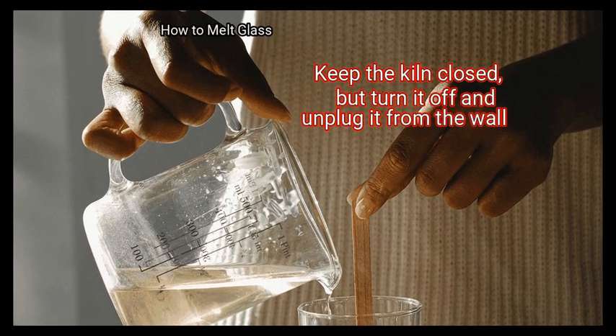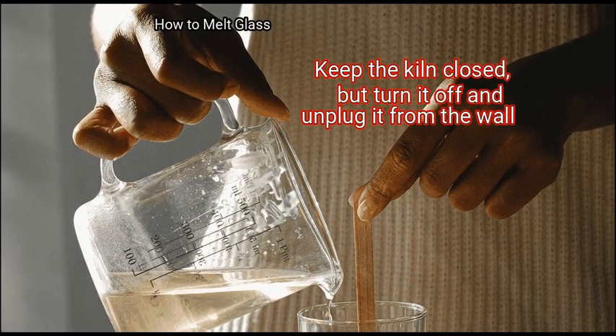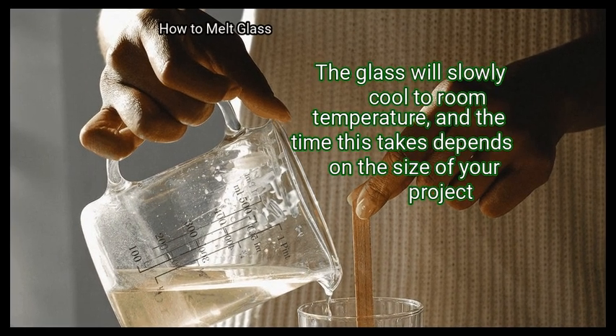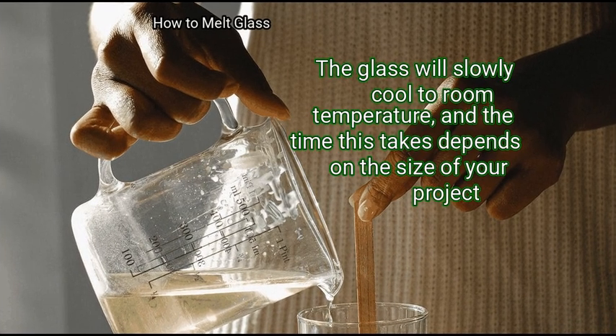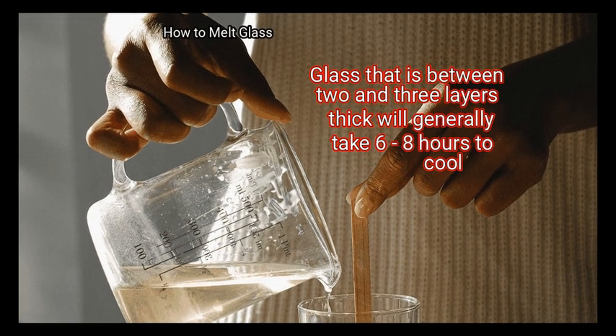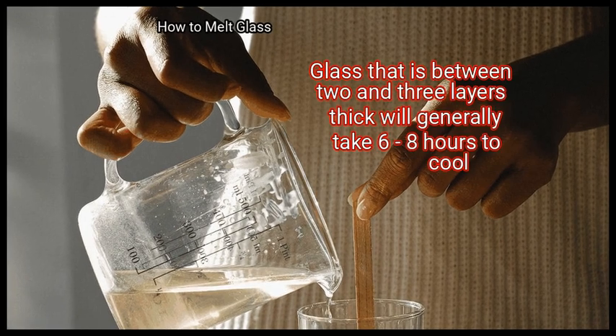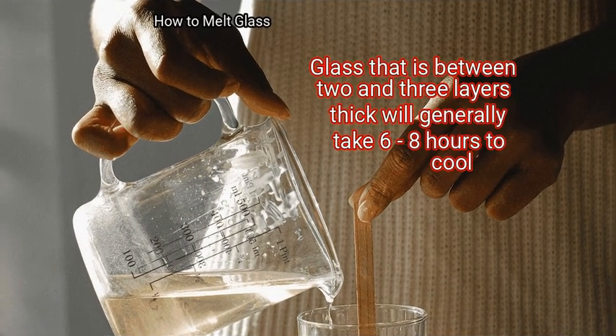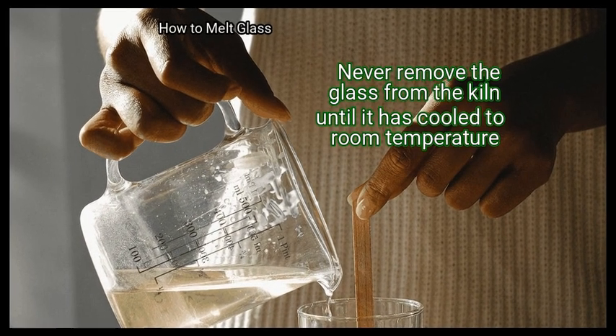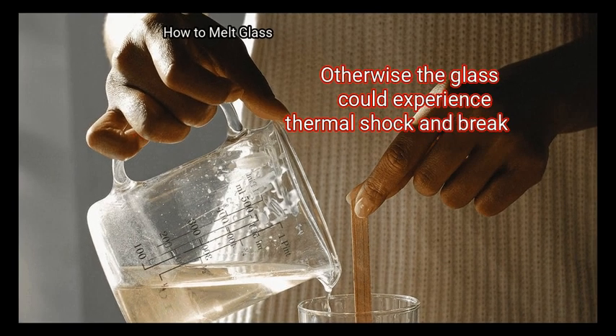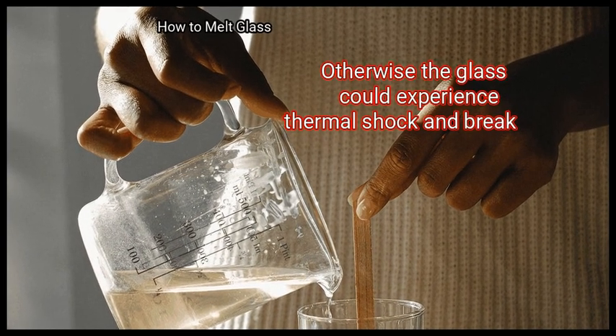Keep the kiln closed, but turn it off and unplug it from the wall. The glass will slowly cool to room temperature, and the time this takes depends on the size of your project. Glass that is between 2 and 3 layers thick will generally take 6 to 8 hours to cool. Never remove the glass from the kiln until it has cooled to room temperature. Otherwise the glass could experience thermal shock and break.